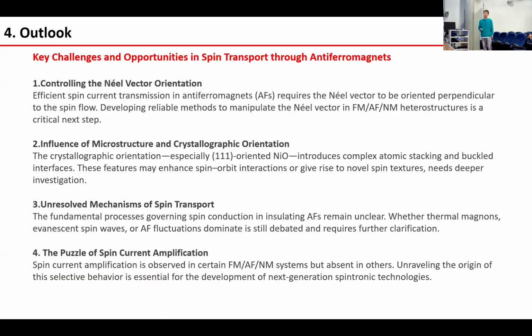So looking ahead, there are several key challenges and opportunities in spin transport through antiferromagnets. First, we need to further study controlling the Néel vector orientation, because efficient spin current transmission in antiferromagnets requires the Néel vector to be oriented perpendicular to the spin flow, and developing a reliable method to manipulate the Néel vector in the heterostructure is a critical step.